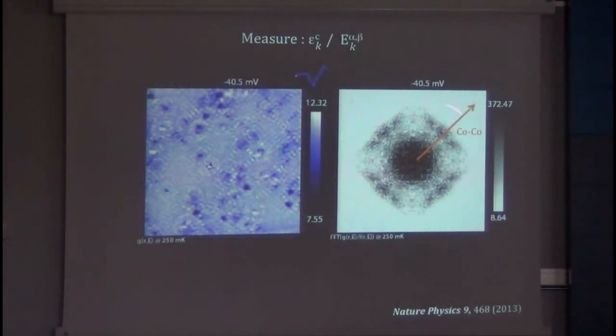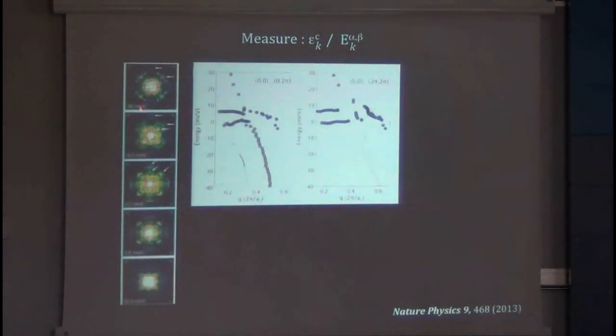So the next thing we could do is examine the part of this movie which changes very rapidly as a function of energy. So this is like minus 4 millivolts up to plus 10 millivolts. And that allowed us to see the light band turn into the heavy band, jump across the Brillouin zone, and turn back into the light band just as expected. And we could do that in a sequence of different directions in reciprocal space and equivalently in momentum space.